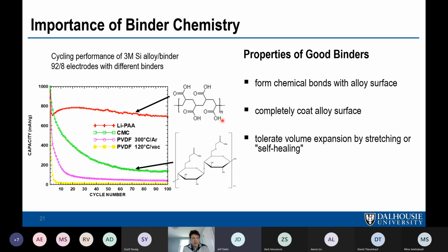You can also do that by lithiating it. So if you have phenolic resin or, what's the other one again? Polyimide, and you lithiate it in the cell, the lithiation of phenolic resin or polyimide carbonizes it. The lithium's reacting with all the oxygen and nitrogen in the polymer and leaving carbon. And so the way that phenolic resin and other conjugated polymers work for alloys is that they carbonize on the first lithiation. Of course, that creates a high irreversible capacity, but the resulting cycling is better than LiPAA in general.